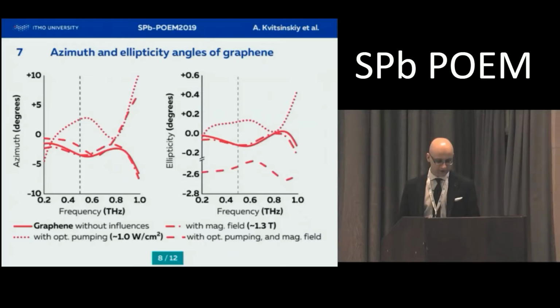Similar results were obtained for graphene on the silicon substrate. Particularly interesting data is from 0.8 to 1 terahertz. The magnetic field does not have so great an influence on the results, as was described in the work earlier. Unlike optical pumping, which turns the azimuth angle relative to the point of origin, the amplitude of the angle values is also about 10 degrees. These results indicate a large effect of the silicon substrate on the final data.